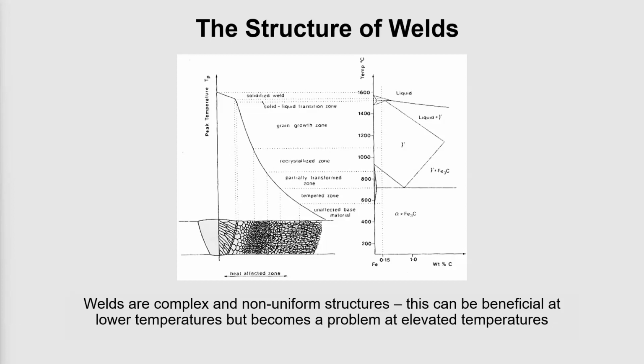That has certain implications for the microstructures of those materials, because at each particular temperature increment, there will be a change to the microstructure associated with that temperature increment. And with the change in the microstructure, that also means there'll be a change in the mechanical properties associated with the material at that local area of the weldment. And so many of you will have heard terms like the weld deposit and the heat affected zone. And in a lot of cases, when those are discussed, the implication is that the heat affected zone is a nice homogeneous structure, and in fact, it's not. It's a very complex structure. There are multiple substructures that develop within the heat affected zone, and each of those substructures has its own unique set of properties that will define how it responds to temperature and stress when it's put into service.